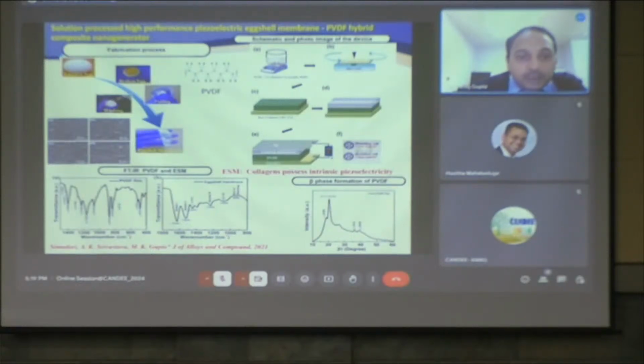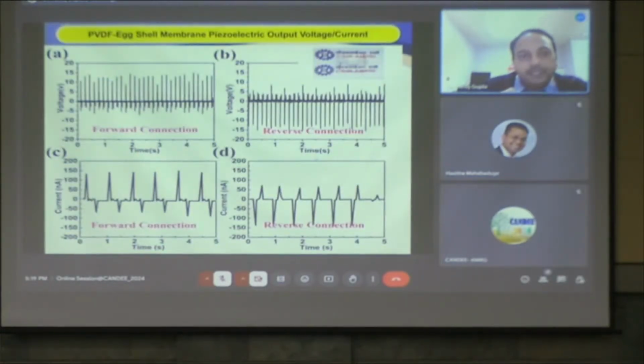So we took this egg membrane and deposited it on the pristine ITO substrate, and at the same time on a polymer film, and then deposited the egg membrane over there, and then two devices were formed: one with the egg membrane alone and one with the heterostructure. You see, very interestingly, it is giving 15 volts. Just a small pressure will give 15 volts output.